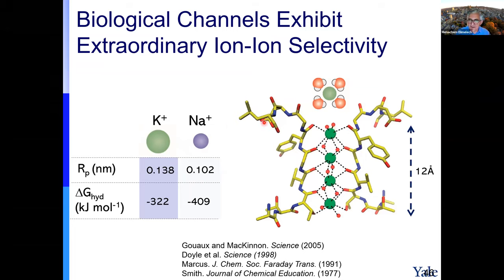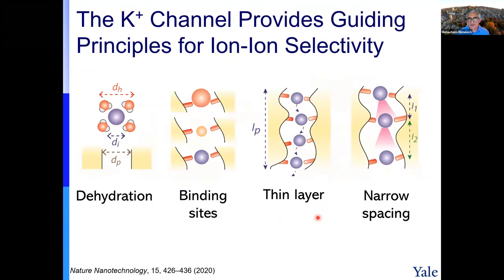And the sodium cannot do it. The sodium is smaller and it will just go through here by diffusion. And because of this binding to these sites and jumping between these sites, you can get a much higher transport rate of potassium. And again, these are the principles. If we want to design a good membrane that can be selective between ions that are almost the same, it needs to have the right size, so when you dehydrate, you still can go through. We don't want it too small, so that when you dehydrate, you cannot go through. We need to have binding sites that will compensate for the energetic penalty when you dehydrate, so the ion will feel stable.